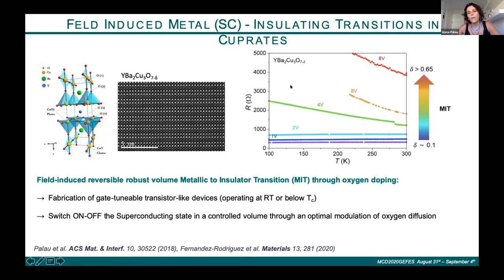We would be able to use this effect to see if we can fabricate devices in a structure which could be used for transistor-like devices that may operate at room temperature, at any temperature above TC or also below TC. We can also evaluate the possibility to tune the ones below TC, to tune the superconducting state, and play with the superconducting properties, modulating the oxygen content in these systems.